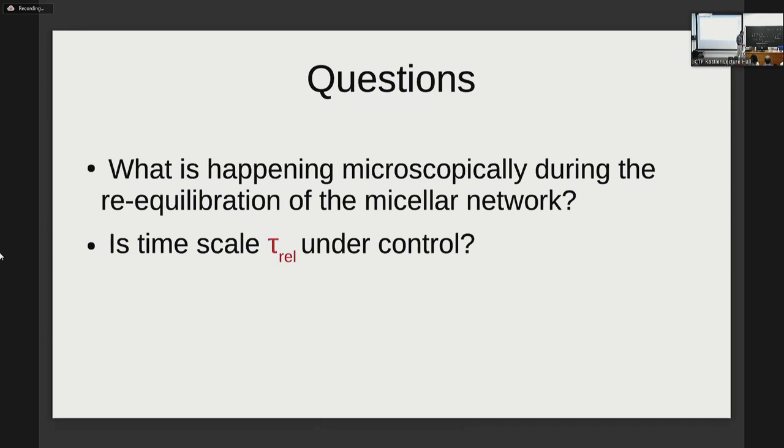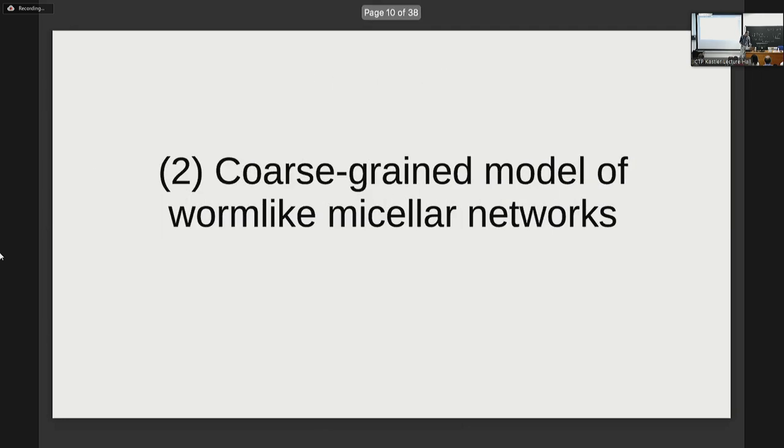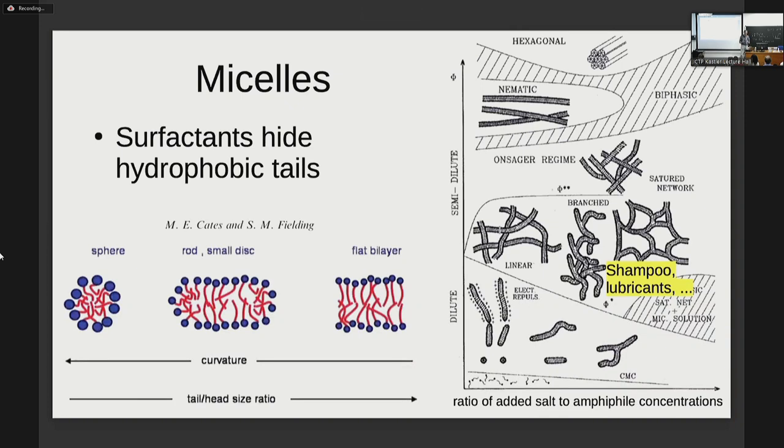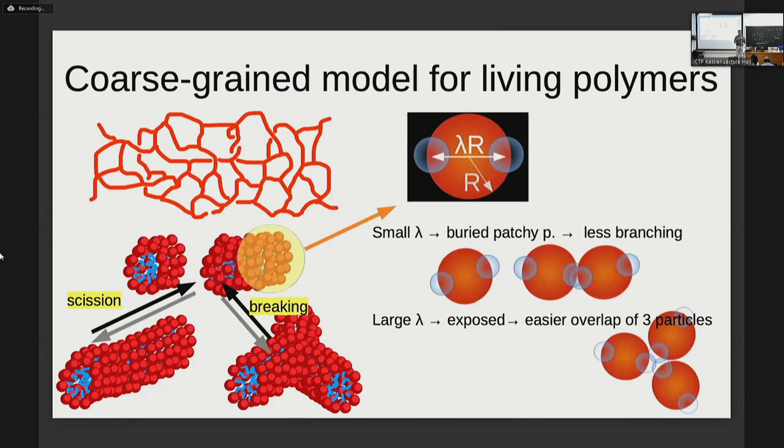So this motivated our interest in the topic because we wanted to understand what was going on at the level of the microscopic relaxations in this complex fluid. Specifically, because eventually there is the chance that the timescales are not correctly evaluated, maybe there is some very long timescale which is not understood. So specifically in this case, we are talking about micelles, which are the surfactants forming micelles, eventually forming structures more complex in a given regime where you, for example, your shampoo and lubricants are examples of this kind, in which you have a network of tubes formed by these surfactants, which are very complex. So they are mostly linear polymers joining in some cross links somewhere, and they are called living polymers because they are all the time attaching and detaching.